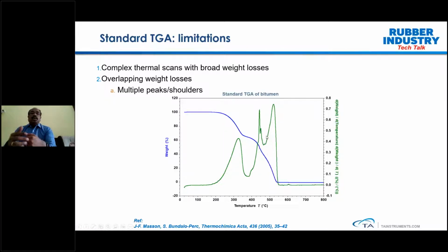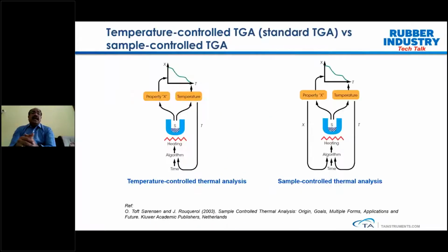When you do the compositional analysis, you should know the onset of decomposition and the endset, so that you can easily calculate the associated weight loss. But in this case, since the transitions are overlapping, it is difficult to calculate exactly when the decomposition is starting. On many occasions, we may have this kind of challenge when running TGA samples. So here comes the advanced mode called high-res TGA, which is basically a sample control TGA.